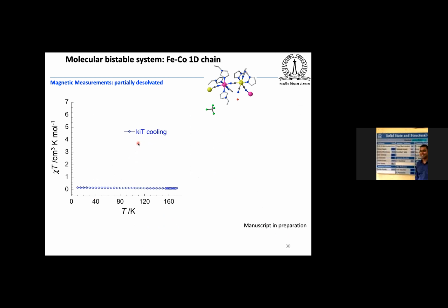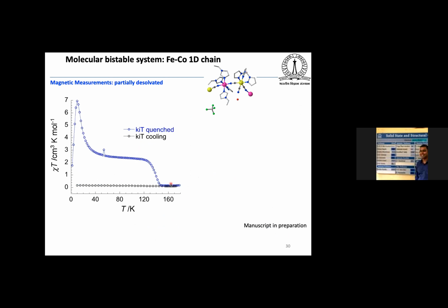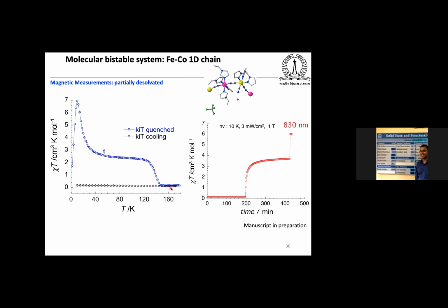And what we have also observed in the χT versus T plot, at approximately 160 Kelvin, this is completely diamagnetic. But we can quench the system, because as I mentioned, after losing the acetonitrile molecule, it is completely paramagnetic, so we can quench the system at low temperature. You can see the quenched state is relaxing back at approximately 140 Kelvin. And then when you cool down the system slowly to low temperature, you irradiate the system using 830 nanometer light. That is why we use 830 nanometer light: from the optical reflectivity measurement, we observed that 830 nanometer light is the irradiating light that shows the maximum conversion between the diamagnetic and paramagnetic states.